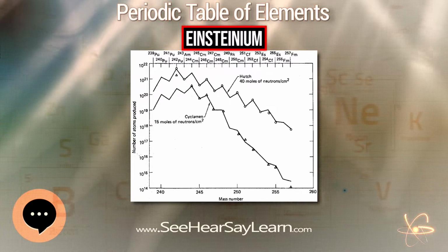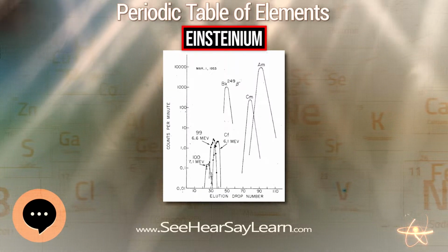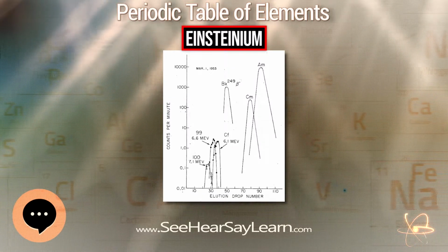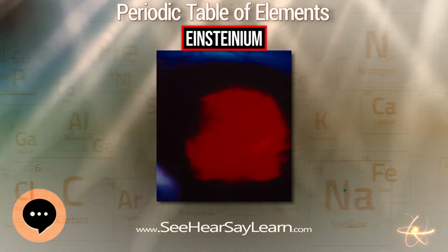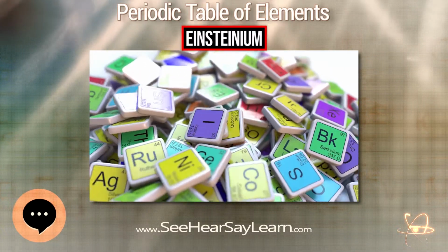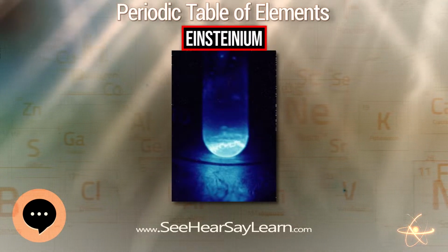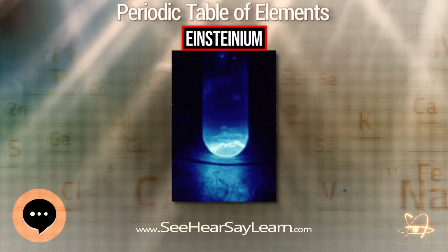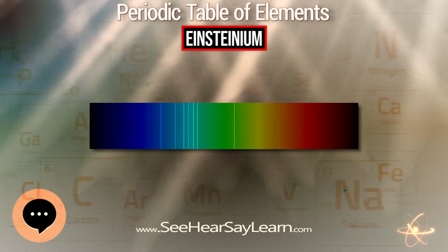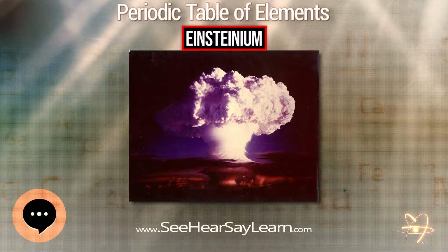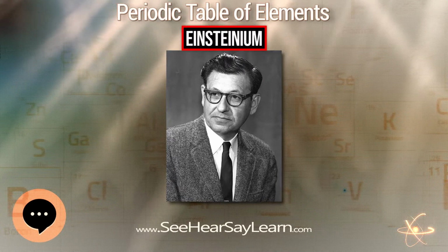The self-damage induced by the radioactivity of einsteinium is so strong that it rapidly destroys the crystal lattice, and the energy released during this process, 1000 watts per gram of 253Es, induces a visible glow. These processes may contribute to the relatively low density and melting point of einsteinium. Further, owing to the small size of the available samples, the melting point of einsteinium was often deduced by observing the sample being heated inside an electron microscope. Thus the surface effects in small samples could reduce the melting point value. The metal is divalent and has a noticeably high volatility.